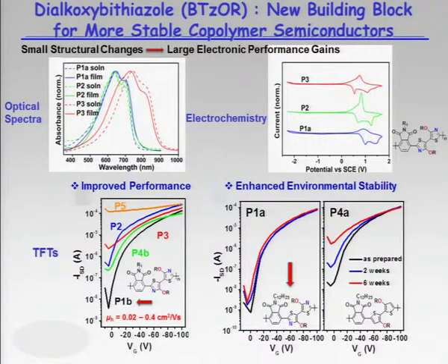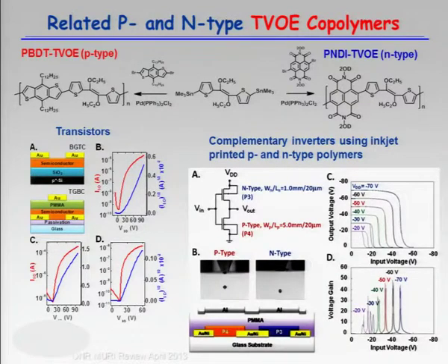And this is lifetime data, and I'm showing you 6 weeks, but I could show you a year, and dramatic enhancements in the stability of the devices by introducing nitrogen atoms in the heterocycle. Finally, we've learned enough about tuning these materials that with this copolymer, so copolymer meaning there's a thiophene, there's this linking group, and then there's this very electron-rich group. These are p-type. We can modify this structure, this intermediate structure, in another way and make it n-type.